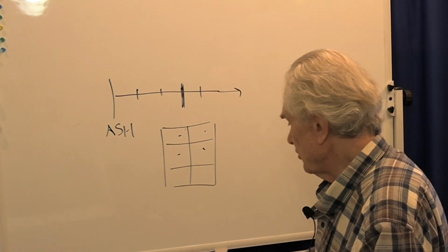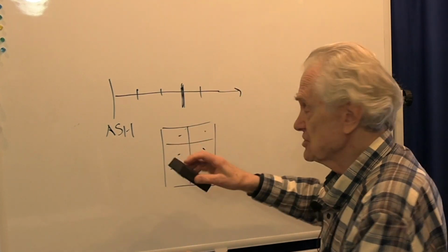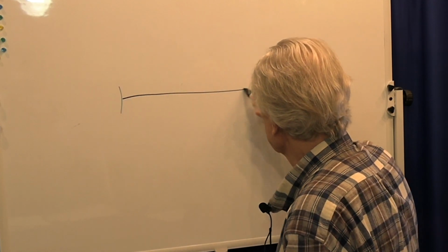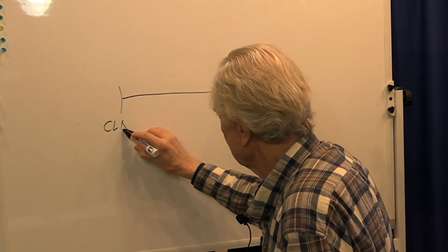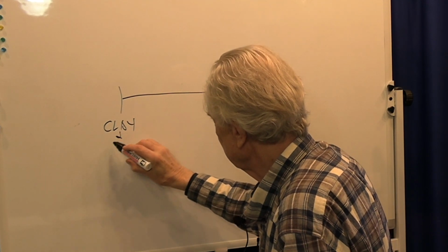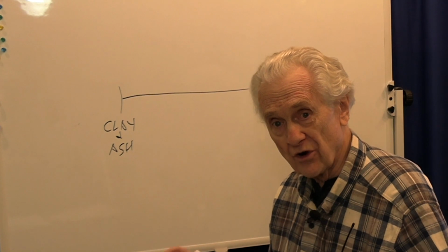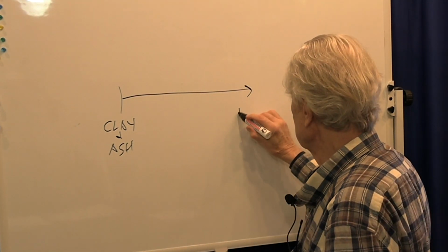The next thing you can do, so this is really basic. At this point, all you have is a mixture of ash and clay, and now you might want to refine it and start looking into other ingredients. What else can I add? Well, I can do another line blend. Only in this case, I can take the clay and ash blend from the first test, the one that seemed to work the best, and now add small amounts of a second ingredient, like feldspar.